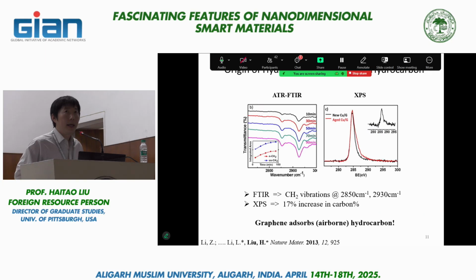On the right-hand side is XPS, X-ray photoelectron spectroscopy. This is a very surface-sensitive technique. It tells you what kind of elemental composition you have on the surface. And the particular peak I show here is the carbon XPS peak. You would expect carbon on this sample because you have single-layer graphene, which is made of carbon, so that is expected. What is unexpected is this broadening.